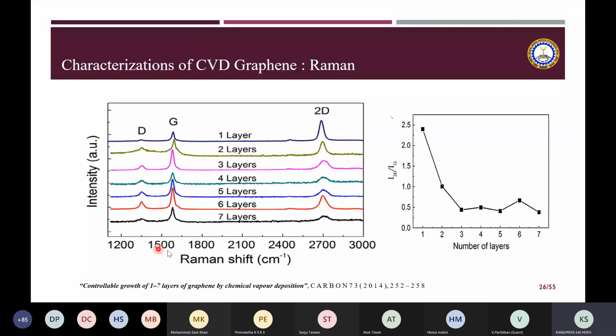This is a study published in 2014 in Carbon, which shows very clearly how the intensity of the peaks changes when the number of layers changes. This is the ratio I2D by IG. You can see this ratio for the number of layers: for 1 layer it is around 2.5 and reduces to about 0.5 when the number of layers is 3. So there is a sharp decrease in the ratio of these two intensities as the number of layers increases, and after that it shows an erratic behavior.